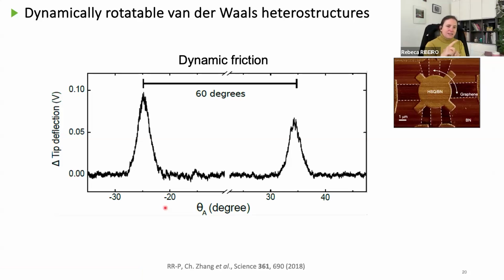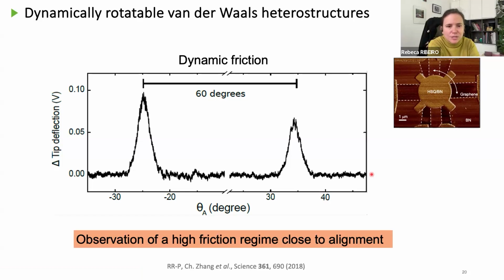We use these handles and the friction detection of the AFM, that is just the lateral bending of the tip, to measure the friction response. And you can see that every time we cross the alignment, so every 60 degrees, we observe a strong increase in the friction, which is reflected by the presence of this moiré superlattice, which increases the friction because van der Waals forces will be stronger at that position, at the line position. So what else can we do?